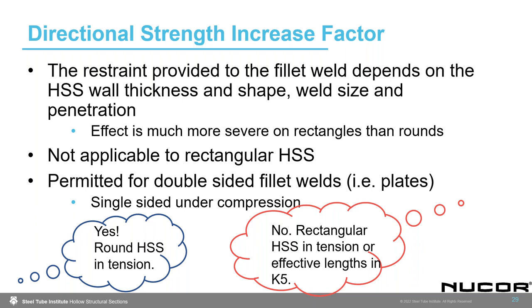The effect of this bending about the weld root is much more severe on rectangles than it is in rounds. I think you can envision that a weld that is round in shape is going to have more restraint to it than something that is along the face of a rectangular HSS, which is more linear. Therefore, the research supported this theory and found that the directional strength increase of 1.5 doesn't result in an adequate safety factor as outlined by the specification.